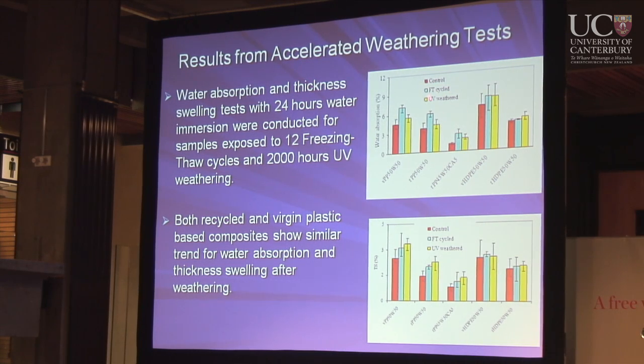This is a control. This is freezing thaw cycles. This is the UV cycles. So a little bit increase, but still quite stable. And then look at the thickness swelling, the thickness changes. If you look at this formulation, it's still quite low, less than 2%. After quite a long time of accelerated weathering and cycling, the material is still quite stable. So from this result, we can claim the wood plastic composite we made is quite stable and also durable.